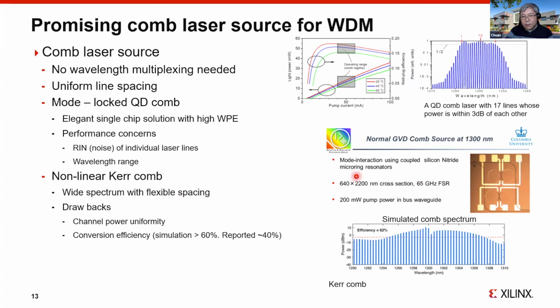I think these are from Columbia, they actually ran the simulation for us when we were talking to them about this. These are, I think, silicon nitride based micro resonators. Basically you pump light into these resonators, then due to nonlinearity at their high intensity, the one single line turns into an array of lines like a comb. You can design these resonators with different size to control the line spacing, and you can control the conditions to get a wide range of lines above a certain power level.